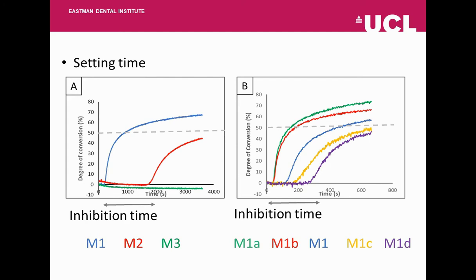The monomer conversion time desired by surgeons also varies depending on their experience. The formulations allow for controlling the level of conversion by changing the levels of BP and NTG-GMA, where we can see on the graph on the right by increasing these components, we can see this obviously also reduces inhibition time, and you need to sort of weigh out what's desired.